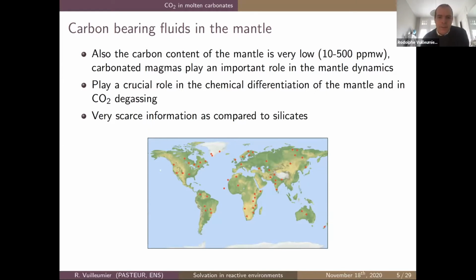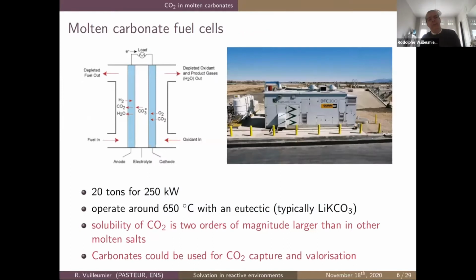In simulation, silicates have been very much studied. There was very little information on the carbonates themselves, which, apart from this geologic application, also have a technological application in molten carbonate fuel cells. Because of their high conductivity and rather low fusion temperature for a molten salt, about 600, you can go down to 550 degrees Celsius, they can be used as the electrolyte for fuel cells. They also have a much larger solubility of CO2 with respect to other molten salts.